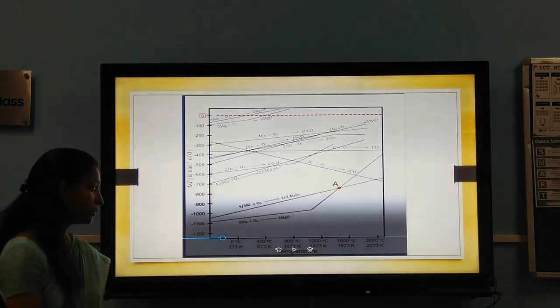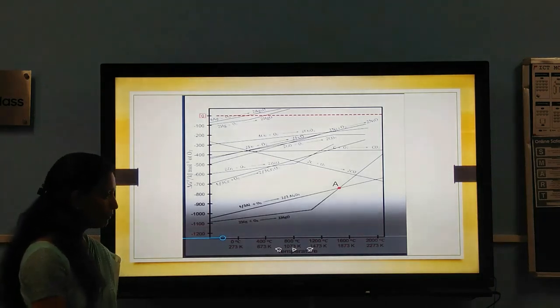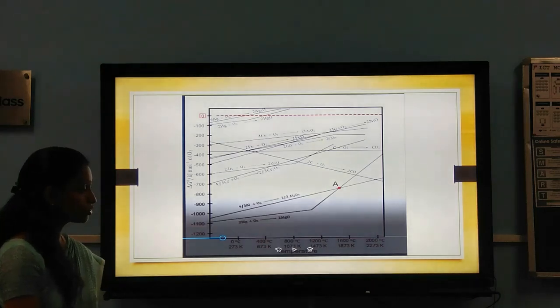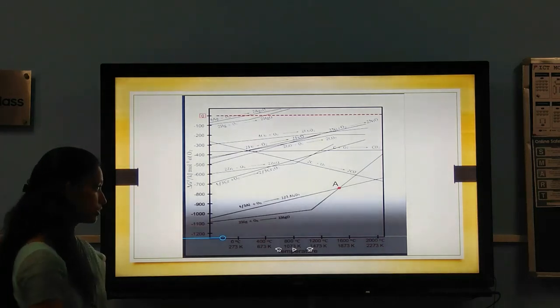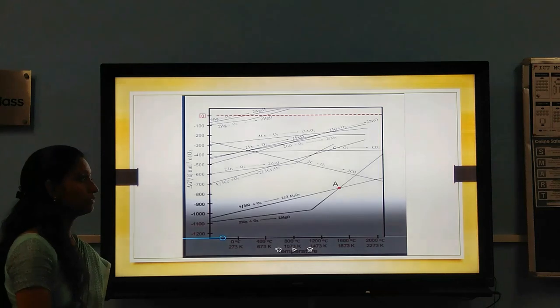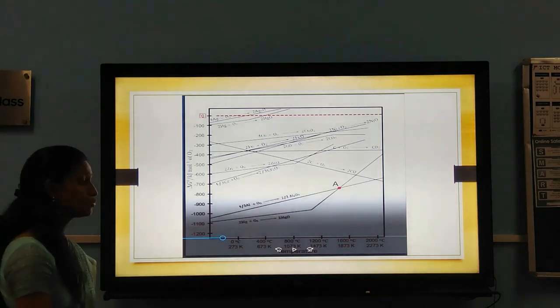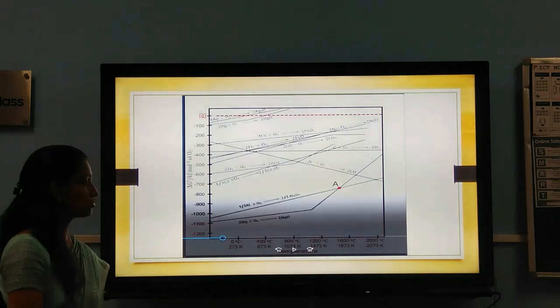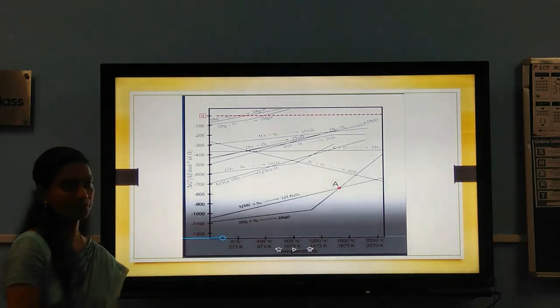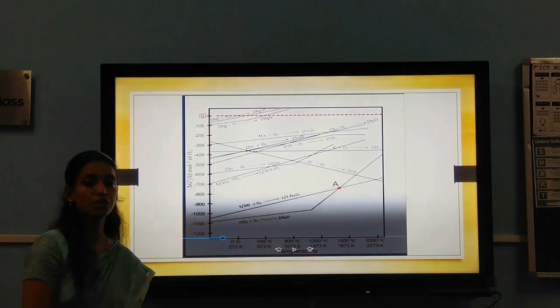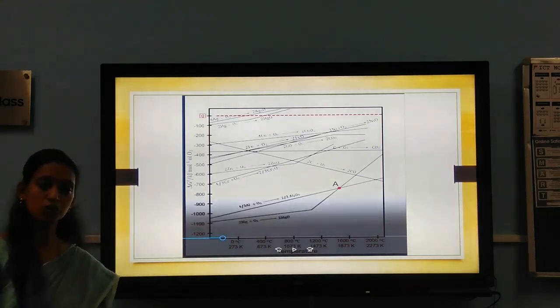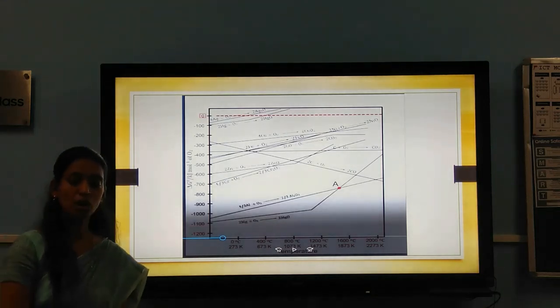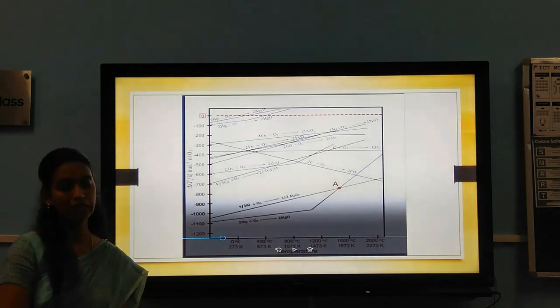Here you can see that above 1623 degrees Celsius, aluminium has the capability to reduce magnesium oxide, and below that temperature, magnesium reduces aluminium oxide. So in such a way, you can choose an appropriate reducing agent and a temperature to carry out reduction of any oxide.